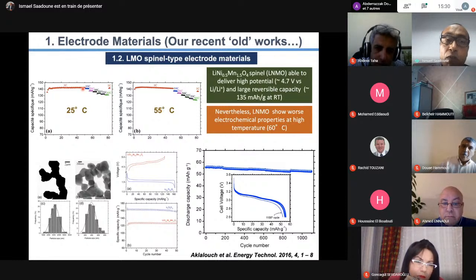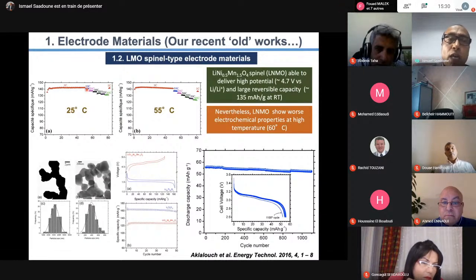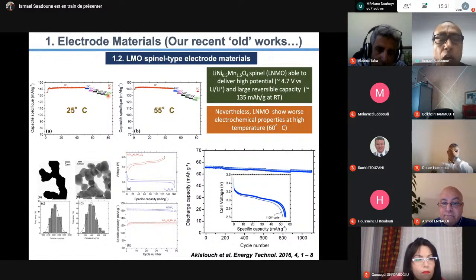And here, 10C, 20C, 30C, 40C - if you have 10C, for example, this means you discharge your battery in 1/10 hour, which is 6 minutes. Discharging at 60C means discharging in 1/60 hour, which is 1 minute. You see we have some preservation - we keep the capacity higher even when we discharge or recharge the battery at fast current.